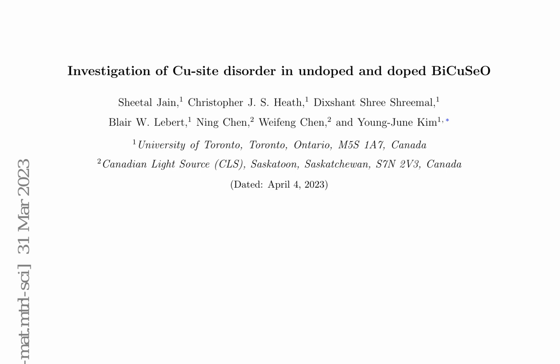vacuum, and heated to 623 K for 12 hours in a box furnace. This intermediate step ensured complete reaction of Se with the elemental metals and reduced impurity phases in the final synthesized sample. The synthesis process enabled the authors to obtain high-quality samples for further analysis.